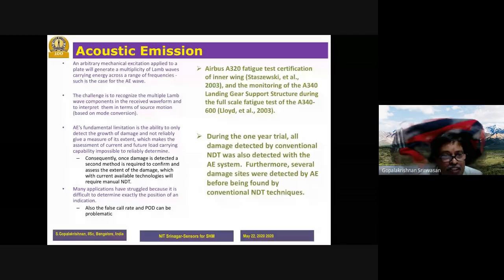The second one is acoustic emission. It's basically like a Lamb wave. A Lamb wave is an ultrasonic wave that travels over a long distance with least attenuation. Whenever you trigger a Lamb wave, you monitor the peak responses, and the peak responses are regions in certain areas. Then you can trigger it wherever you want, not at a specific location. You don't need prior instrumentation. You can actually put a sensor when the aircraft comes to the hangar and do it. But the problem here is that acoustic emission has instances of giving false alarms. It can trigger panic even in a region where there is no damage. So it requires another method to verify the results you got from acoustic emission. That's one of the greatest disadvantages here.